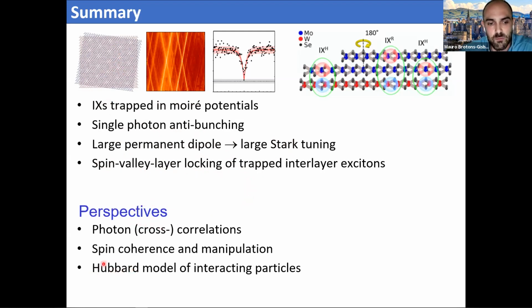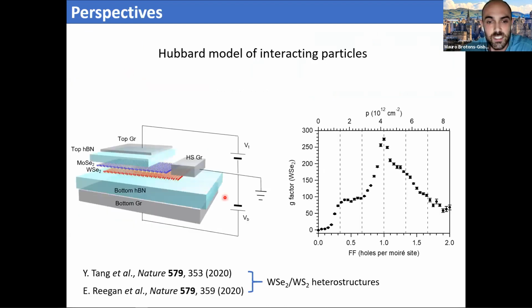The one that I'm most interested in right now is the Hubbard model of interacting particles in this moire superlattice. And before I conclude, I'd like to show you the results for a sample that I have right now in the graphene, where in these devices we can also have an extra contact and change the doping in the layer, and this way we can control the number of holes, or the particles, that we load in our pockets in the moire lattice. And if you measure the G factor of the excitons as a function of the filling factor of holes, we see a huge change in the G factor, which is telling us that we're observing some phase transitions in this material, right? As recently reported in these papers for other heterostructures.